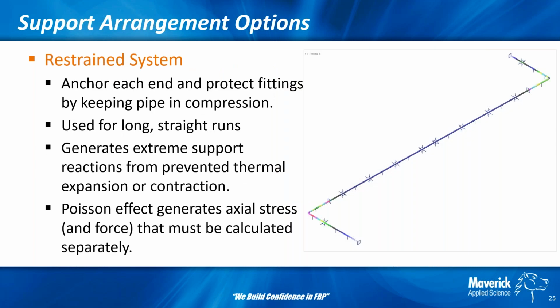An older method of supporting FRP pipe that is still sometimes used today in certain situations would be a restrained system. So basically you anchor each end and you protect the fittings, you keep the pipe in compression. It's fairly strong in compression, so this is really used for long straight runs. Rule of thumb, I would say, is somewhere around 300 foot between anchors. So let's say you had a 600 foot straight run of pipe, you might need 3 anchors in that run.